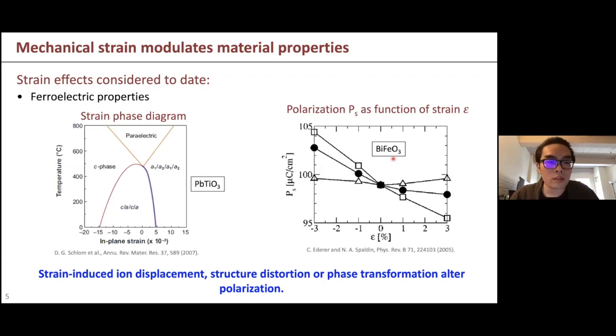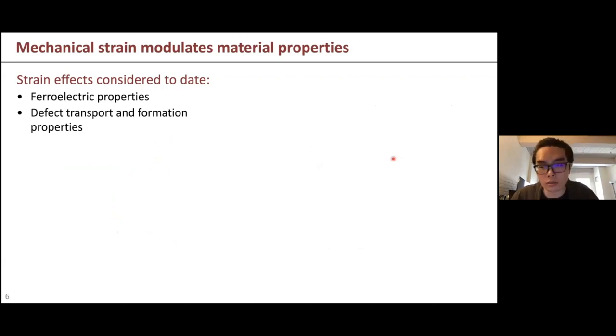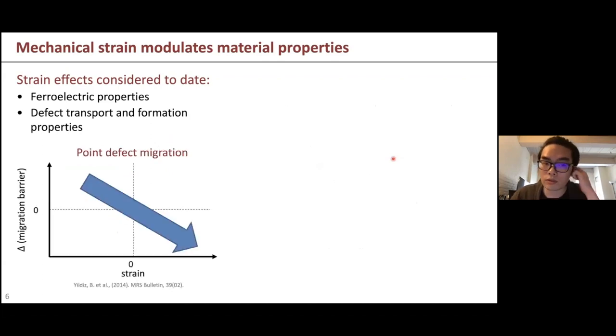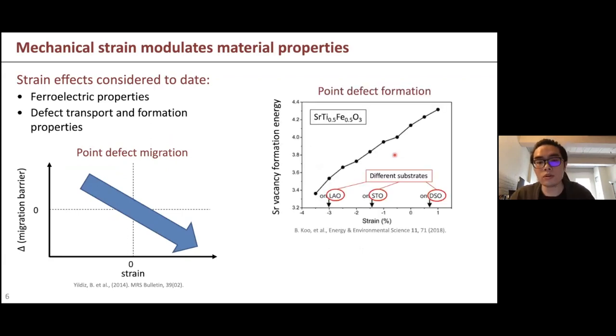The second part is what we are more interested in, which is how the strain can change the defect formation and the transport property. In general, it is believed that when we apply the strain in tension, meaning stretching the material, we can decrease the migration barrier of the point defect, in this case, oxygen vacancy. So if we apply the tensile strain, we can enhance the conductivity of the whole device. Furthermore, if we apply the strain, we can also change the formation energy of the defect, because the conductivity is the product of the carrier concentration and the carrier mobility. So we also have to care about how many carriers we have. In this case, the line is just a simulation study for the strontium vacancy formation energy.